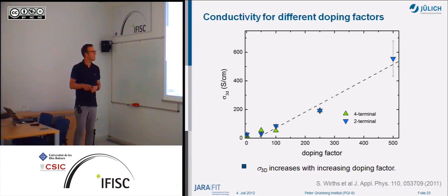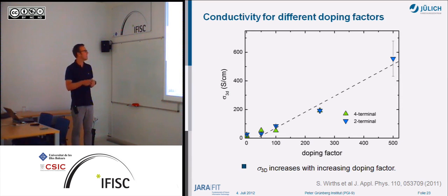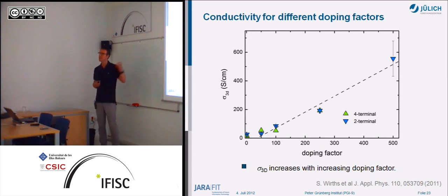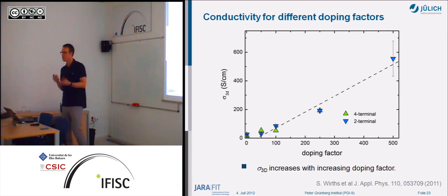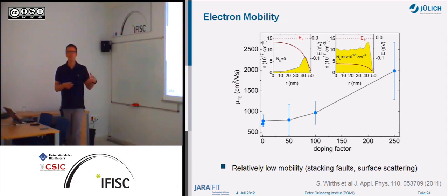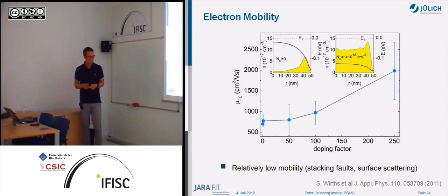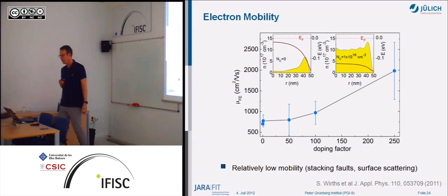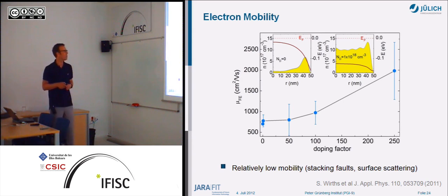What you can see here, this is the increased doping. You see that the conductivity is increasing, so you have a large increase of conductivity, and this gives you an additional degree of freedom. So if you would like to make transistor structures, you can design the conductance of your channel to optimize the transport in the nanowire. And of course, if you do field effect transistor measurements, you can look at the mobility. You see that if you increase the doping, you increase the mobility.